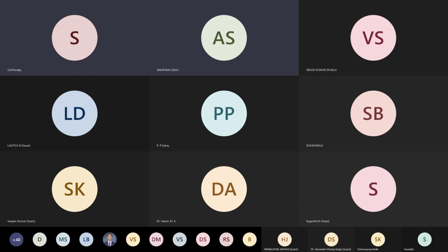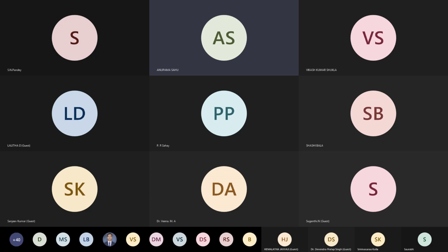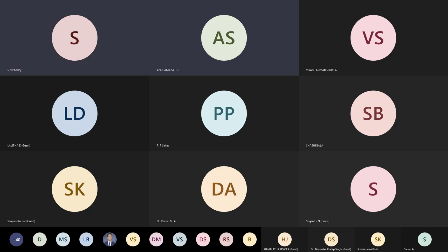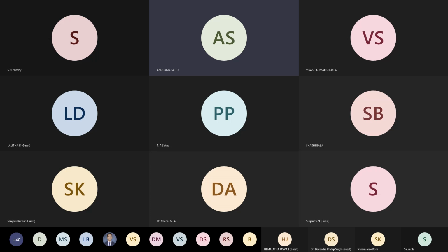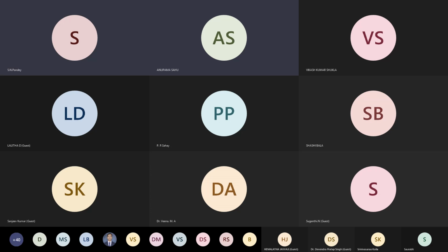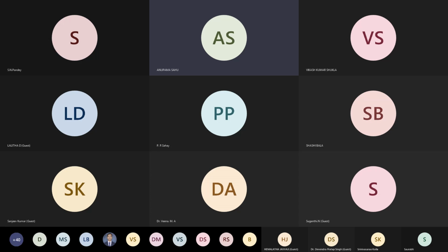You have shown, sir, that conductivity and porosity are both important for supercapacitor electrode application. Right. So is it that porosity and conductivity are inversely proportional? Because during my research, where we get a low specific surface area activated carbon material, we find graphitic behavior and more conductivity. And in some activated carbon materials we find a high specific area, but we get XRD amorphous peaks, and the activated carbon electrode materials are less conductive. So can we say they are inversely proportional, or how are they interrelated for the same material?